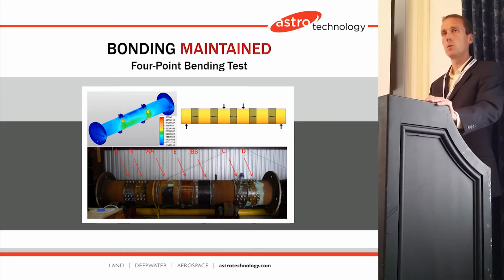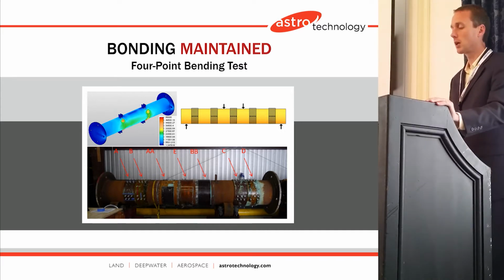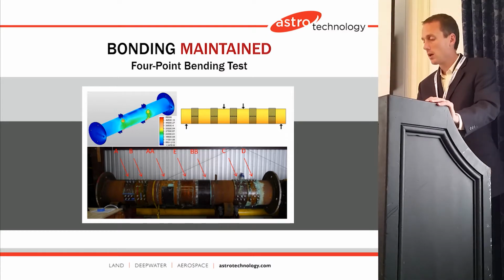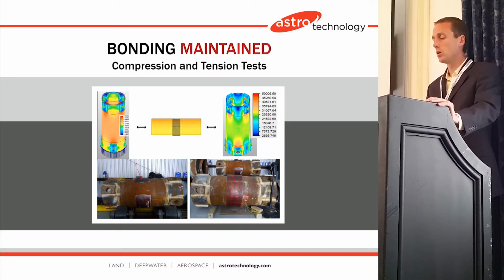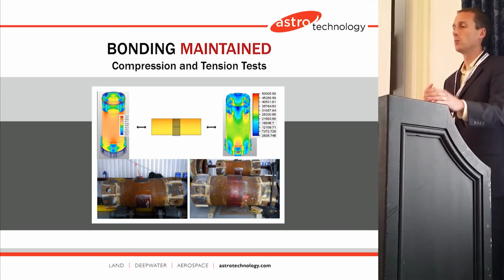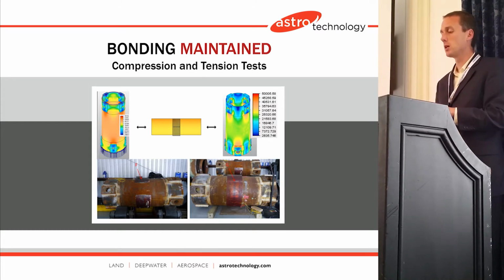And so what we did with this is a finite element analysis. There you can see in the upper left the sample. We are looking for localized points of fatigue and strain. And there you can see with the 4-point bending test, the instrumented clamps as well. So I'm going to go forward. We also did compression and tension tests. Now these were important on this tension leg platform, both the bending but also the compression and tension.